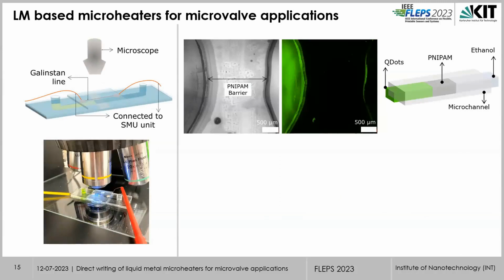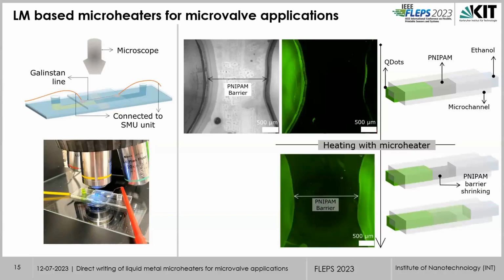When we apply some bias, initially it looks like this: the PNIPAM is in between, with the fluorescent quantum dots on one side and ethanol on the other. When we apply bias and the microheater heats the substrate, the PNIPAM, which has a critical temperature of 32, shrinks, and as it shrinks, both can move, and it looks like this after the shrinking. So we can see this controlled mixing of different materials or different solvents.